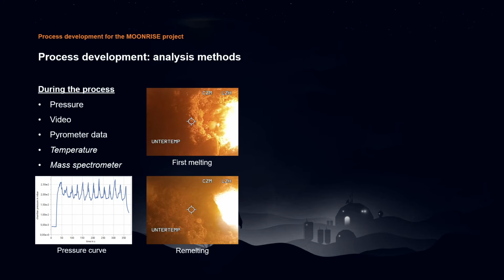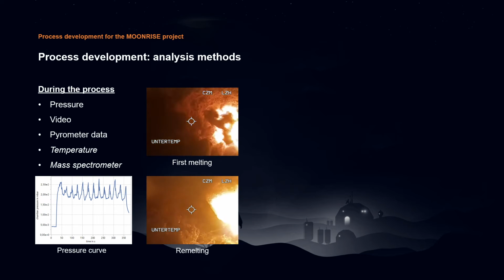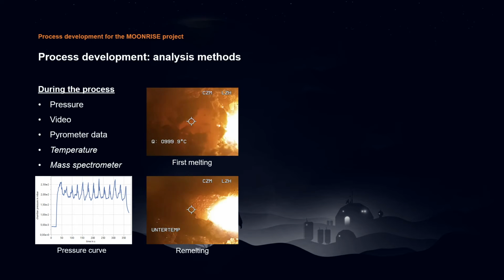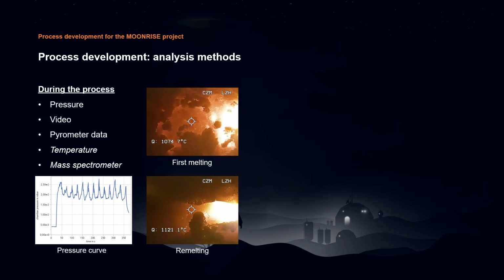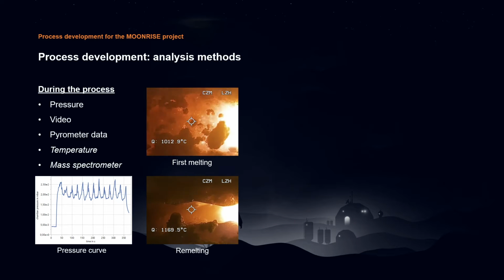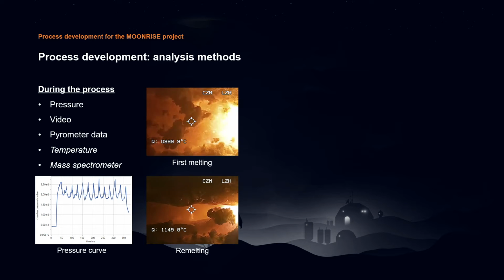And then we also have some videos that we capture, and we gather pyrometer data. As you can see here in these videos, they're working perfect. On the top, you can see the first melting of the raw regolith simulant, and on the bottom you can see the remelting of the already solidified sample. By the way, these temperatures are not real.